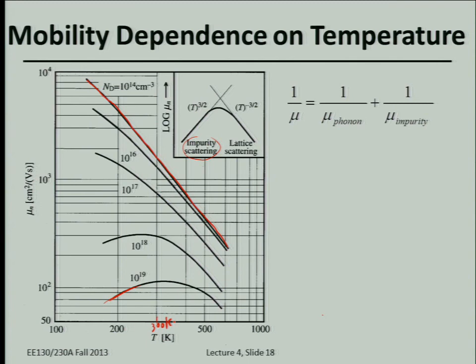Then as you change the temperature, yes, if you lower the temperature, you'll start to see the mobility drop off because of more time spent near an ionized atom, and so it'll affect the mobility more. Okay, but so does that answer your question? Sort of, I mean, most of the time for moderately doped or lightly doped semiconductor, as you increase the temperature above room temperature, the mobility goes down. So conductivity degrades. But for really heavily doped material, it can actually be the opposite. So it really depends on how heavily doped your semiconductor is.